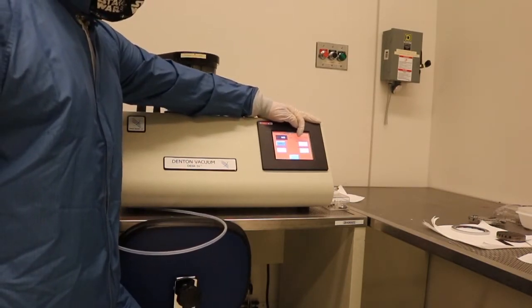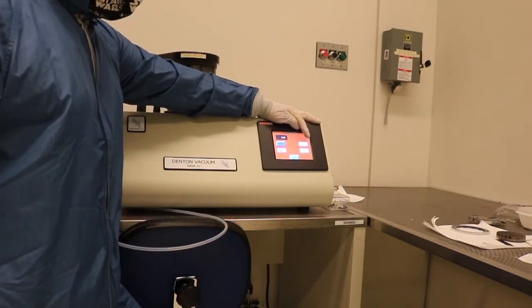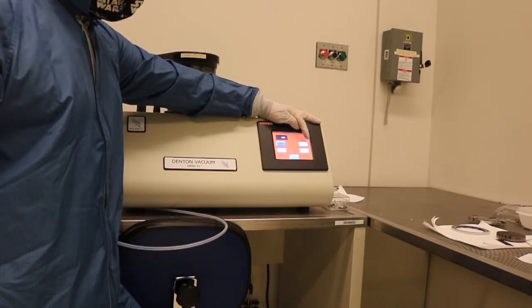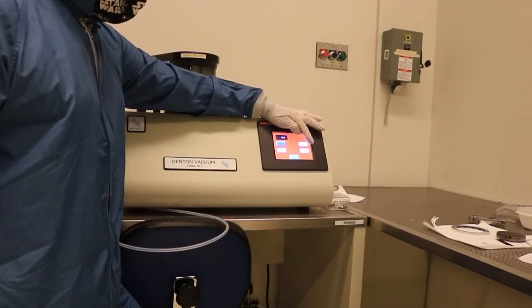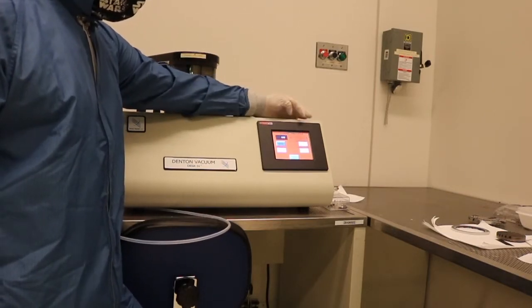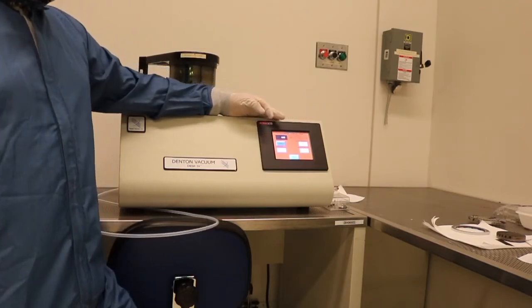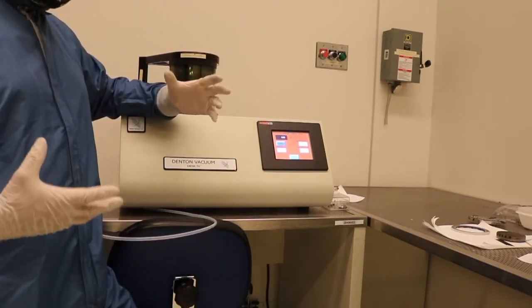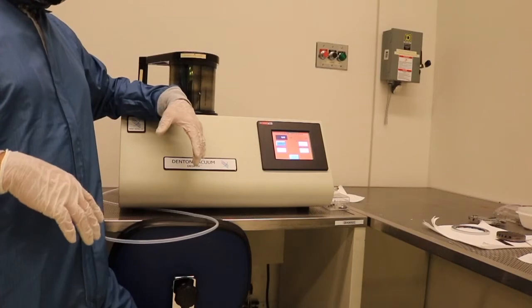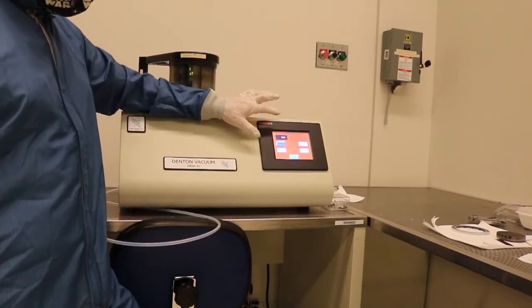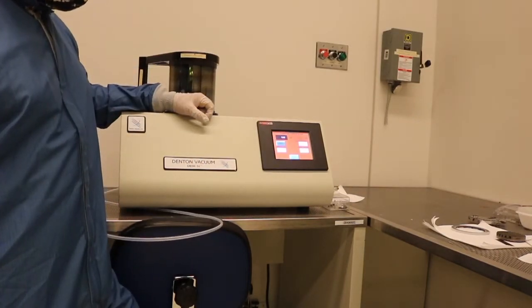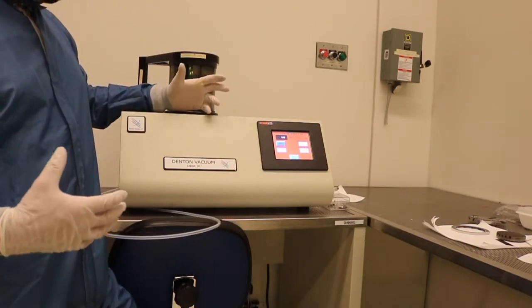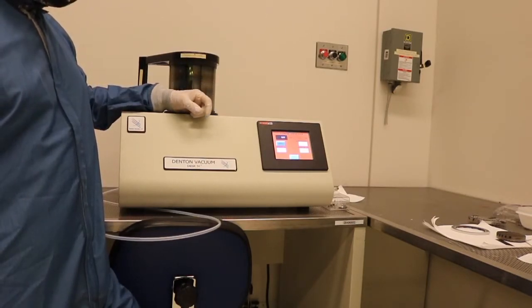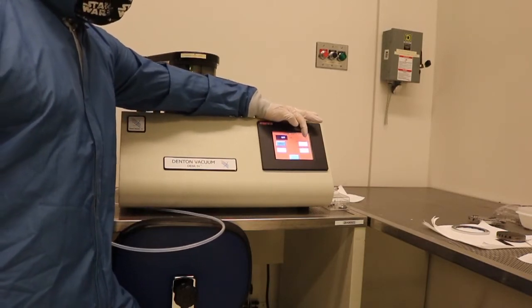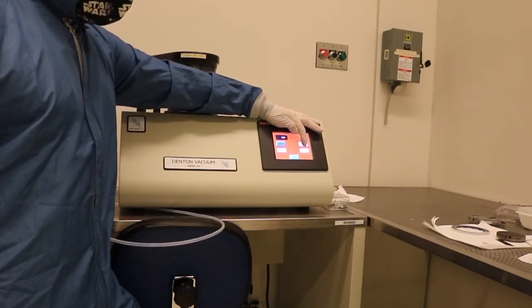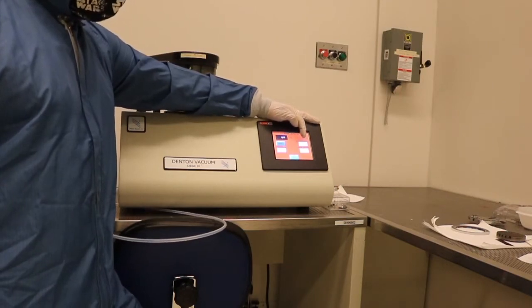The other options that we have here is the sputter set point. That's how much power you're going to utilize out of the total power supply settings, and then how long the sputter time would be for. So right now 30% typically gives us the best or the lowest possible energy at which we would obtain a stable plasma. And then of course our sputter time is now set to 30 seconds. Typically the longer you coat, the thicker your coating will be. So to increase coating thickness, we could either increase our time or we could increase our power supply setting.